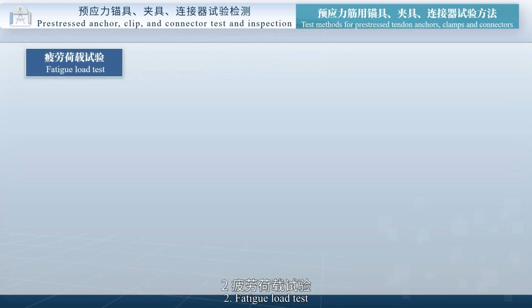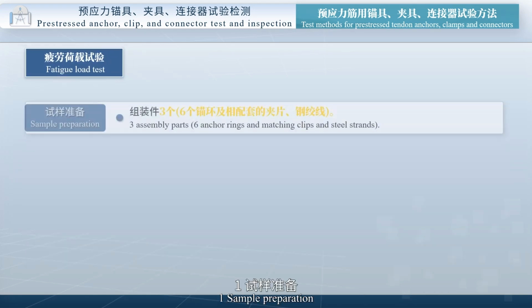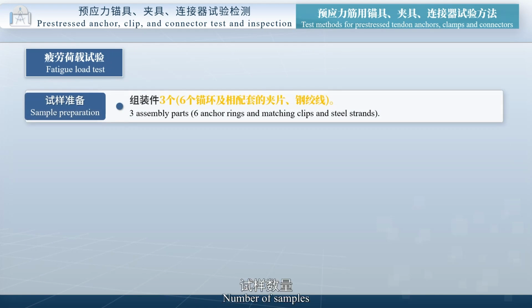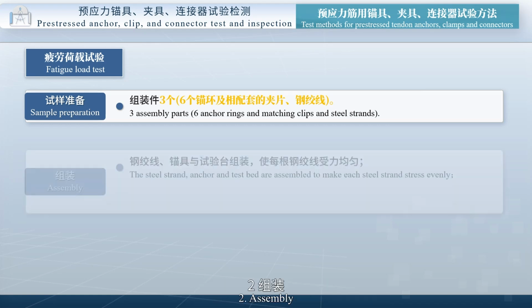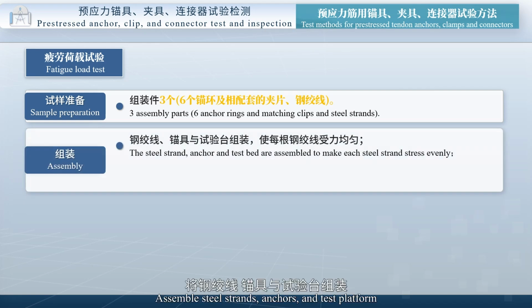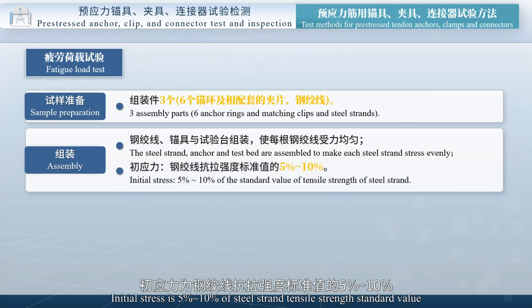Second, fatigue load test. 1. Sample preparation. Number of samples: 3 assemblies, each with 6 anchor rings with matching wedges and steel strands. Second, assembly. Assemble steel strands, anchors, and test platform. Ensure uniform force distribution on each steel strand. Initial stress is 5% to 10% of the steel strand tensile strength standard value.